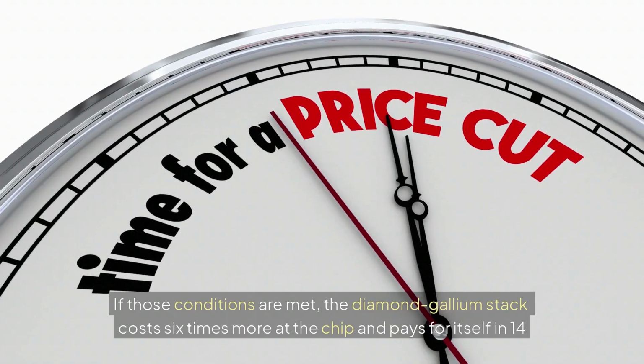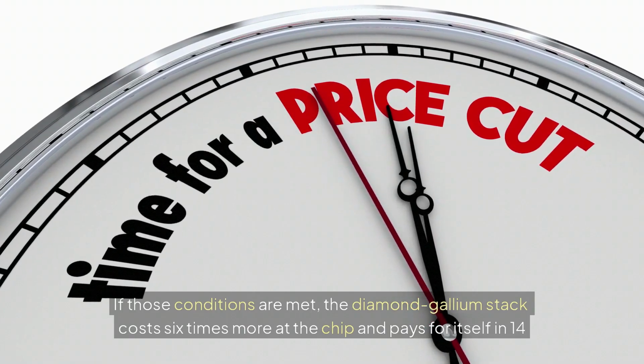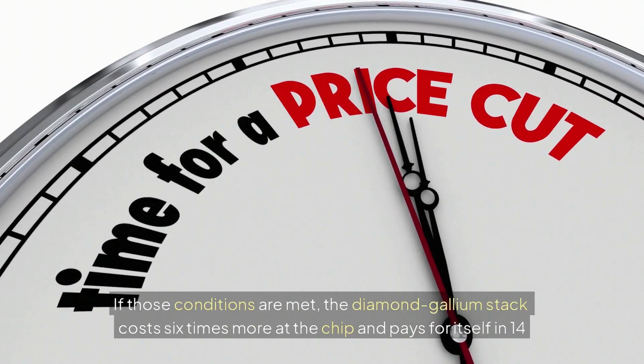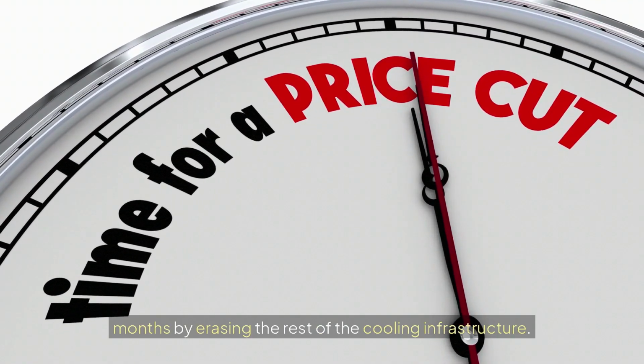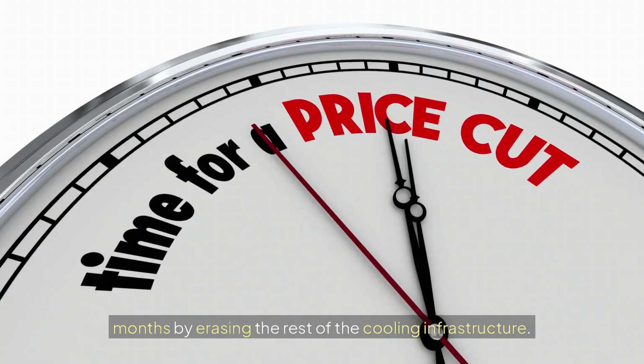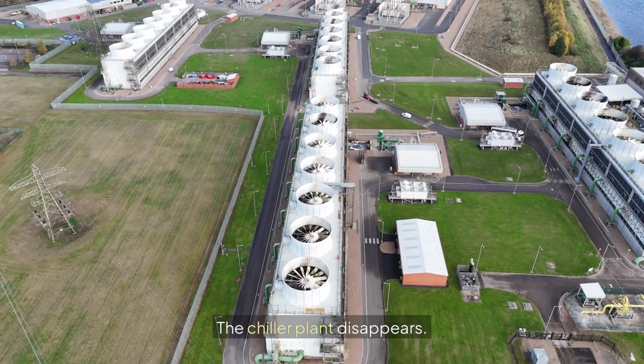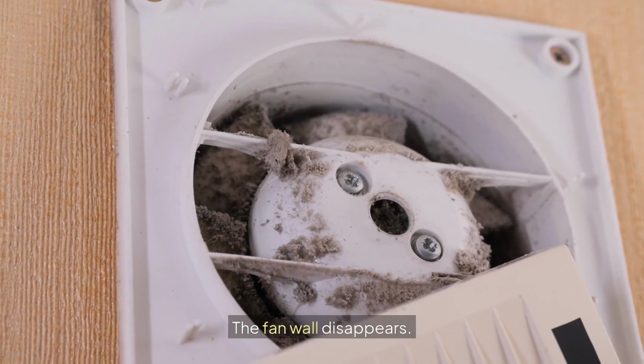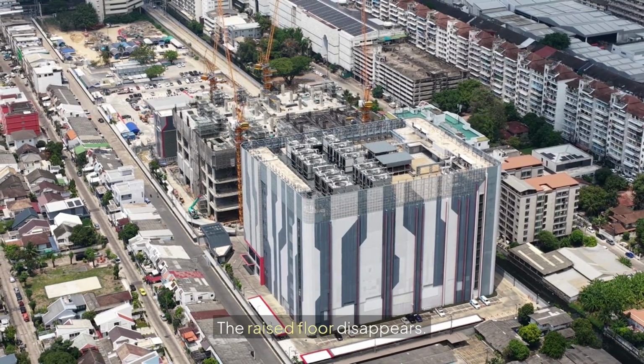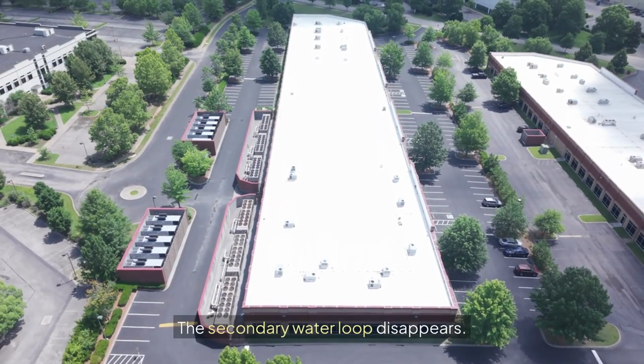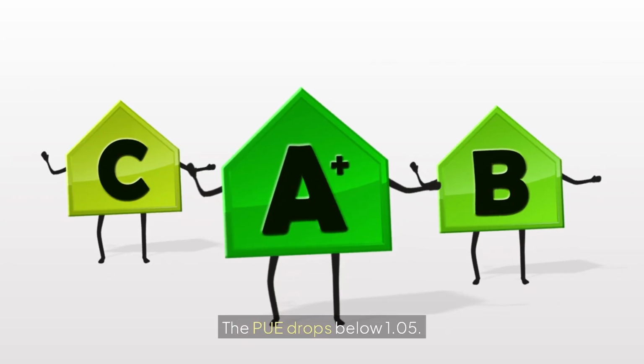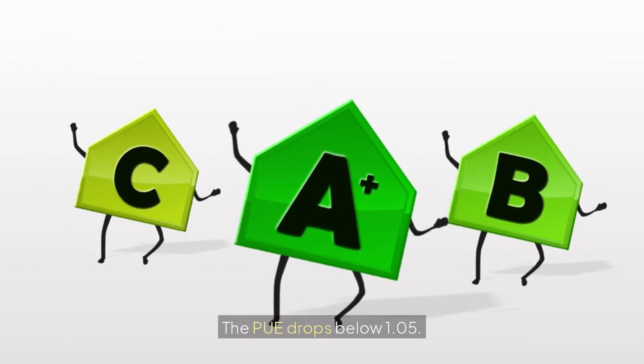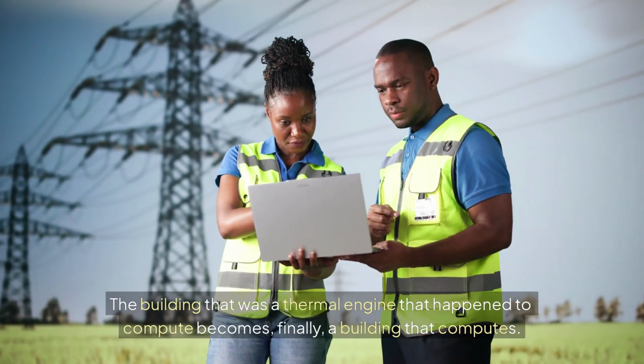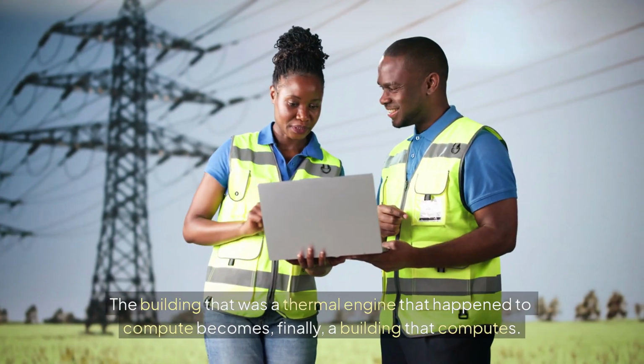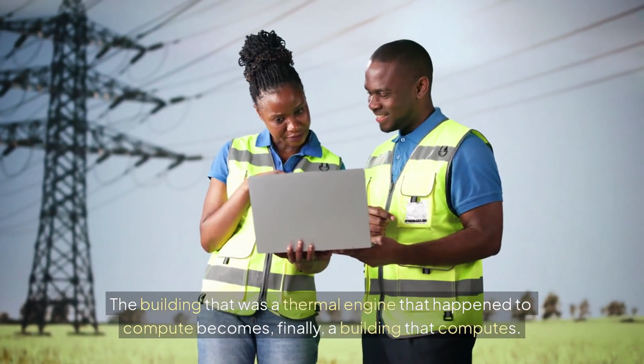If those conditions are met, the diamond gallium stack costs 6 times more at the chip and pays for itself in 14 months by erasing the rest of the cooling infrastructure. The chiller plant disappears. The fan wall disappears. The raised floor disappears. The secondary water loop disappears. The PUE drops below 1.05. The building that was a thermal engine that happened to compute becomes, finally, a building that computes.